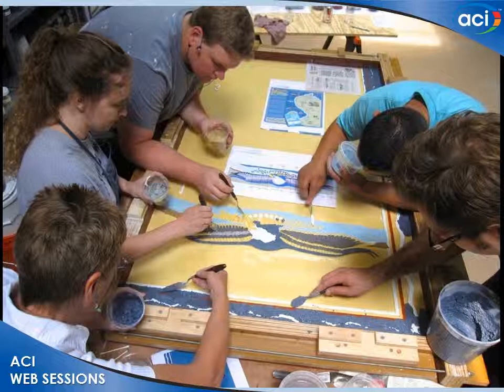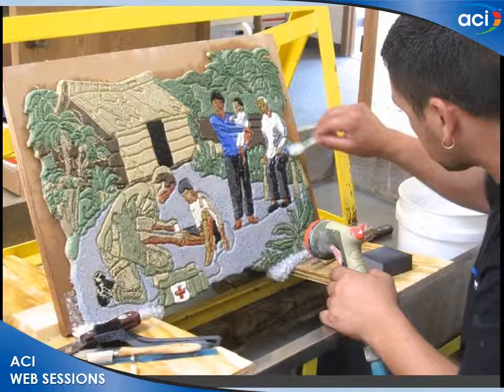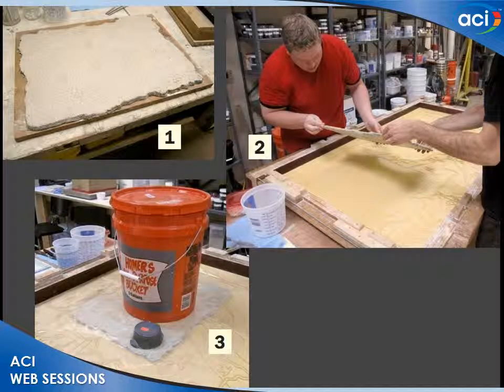It would take usually 7 to 8 of us working 10 to 12 hours in a day to do one precast panel, when we got to that point. However, in terms of time, we could only mix and place about 25 colors. So on some panels that had 35 to 40 colors, we had to do the artwork as separate inserts. Those are half-inch thick with a fiber-reinforced backup mix in there. Done everything like we did normal casting.